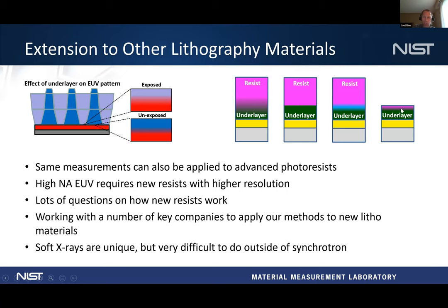And then there's also a lot of interest in looking at the underlayer after you remove the resist to see how any sort of residual aspects of the resist might be changing the chemistry of the underlayer, particularly if they mix a lot, you might not be able to get all the components of the resist back out.